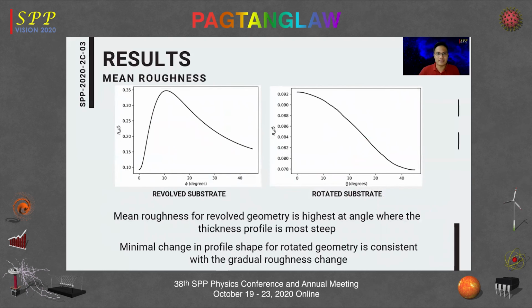Now, for the mean roughness, as you can see in this figure, the mean roughness for the revolved geometry is highest at an angle where the thickness profile is more steep, which in that case is at around 10 degrees. On the other hand, there is minimal change in profile shape for the rotated geometry. And as you can see, the mean roughness changes by a very small amount as compared to the revolved substrate.